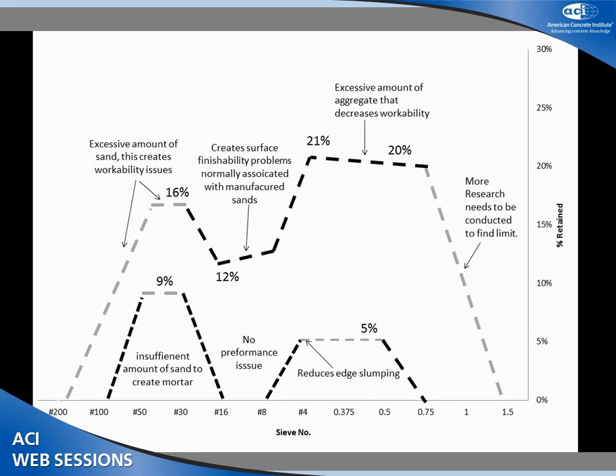We came up with what we call the tarantula curves from those 350 mixes and 4 different coarse aggregates. It looks like a big spider — that's the head over here, that's the body, those are the legs. Every single boundary has a reason why it's there. There's a given reason why we can't use too much number 8 or number 16 material — it causes finishing issues. But if you can keep this below 12%, you're going to be okay from our data.